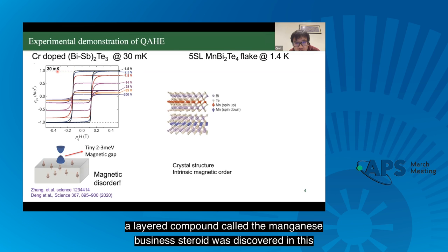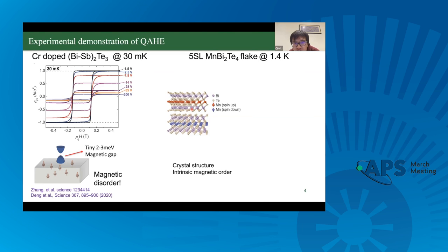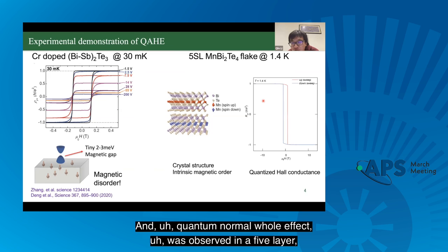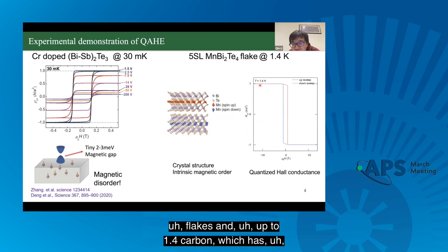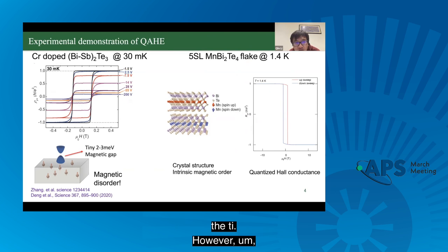Later, a layered compound called manganese bismuth telluride was discovered. This layered compound has layer-dependent topological and magnetic properties. The interlayers are coupled antiferromagnetically, so whenever you have an odd number of layers, there's an uncompensated layer. The quantum anomalous Hall effect was observed in five-layer flakes up to 1.4 Kelvin, which is an improvement compared with the dilute magnetically doped TI. However,